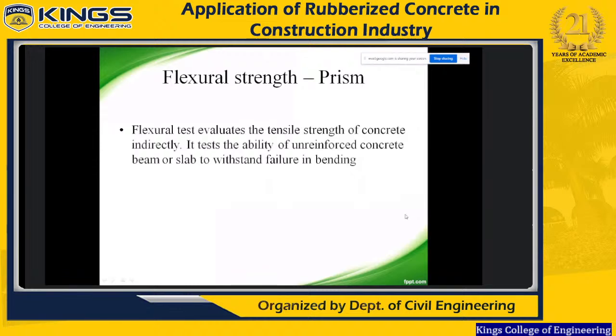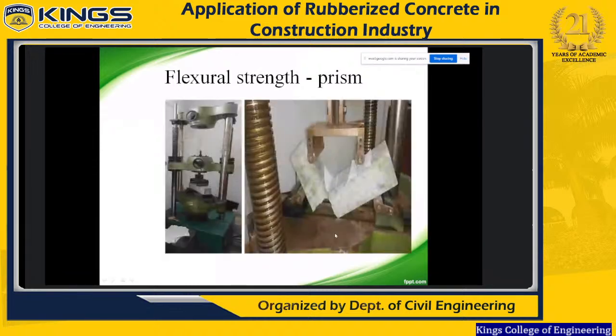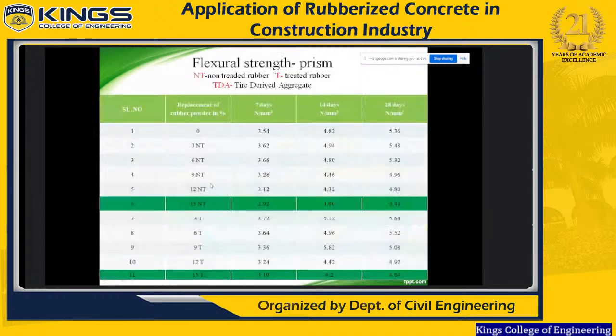Next is finding the flexural strength of concrete in the prism. We carried out the test on the prism, a small beam called a prism. We mark it, put it on and apply load. The flexural strength values of the prism show good results at 15% of non-treated rubber. For treated rubber also, 15% replacement, slightly increasing.